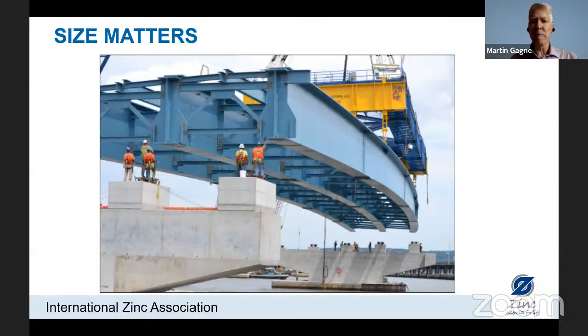So both processes, hot dip galvanizing and thermal spray zinc, are very compatible. They can be used with each other without issues. Generally, hot dip galvanizing is a less expensive process than thermal spray zinc metallizing. But then again, if the size becomes an issue, thermal spray zinc metallizing is the only option to get a metallic zinc coating on the steel for the maximum corrosion protection.